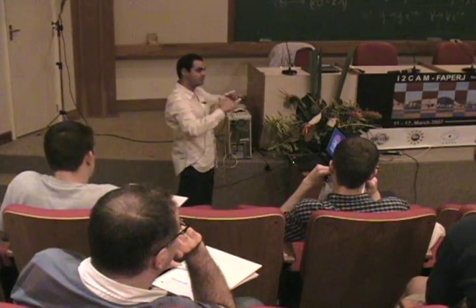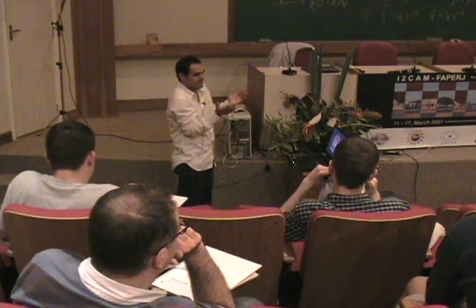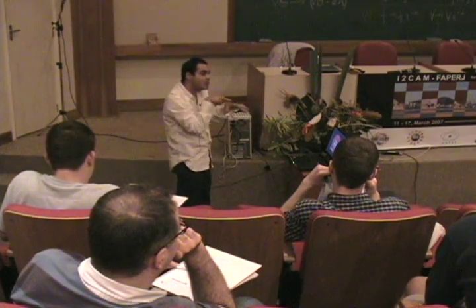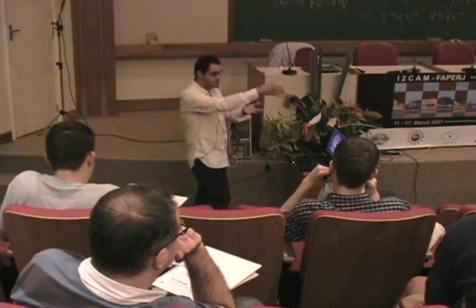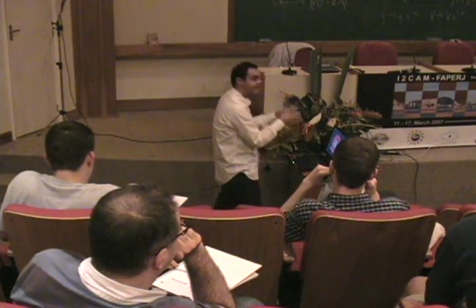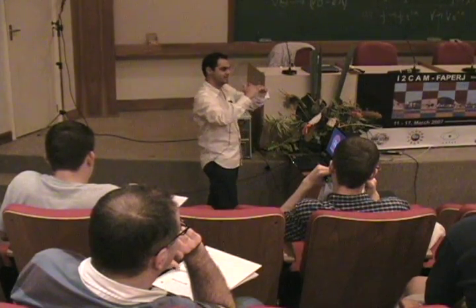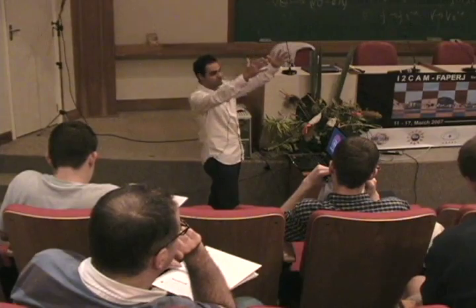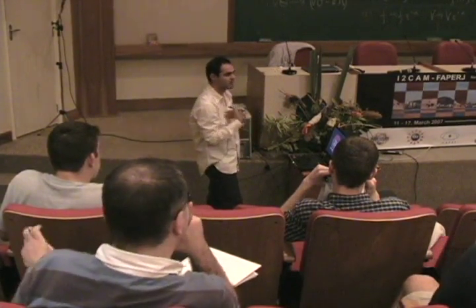Like I said, the c over a is not the only ingredient, of course. You change the strength of your fluctuation. But the local symmetry, in my opinion, determines it; c over a is an effect on the local symmetry. And the change in Tc between CeCoIn5 and PuCoGa5 is, of course, related to the strength of the fluctuation, in my opinion.